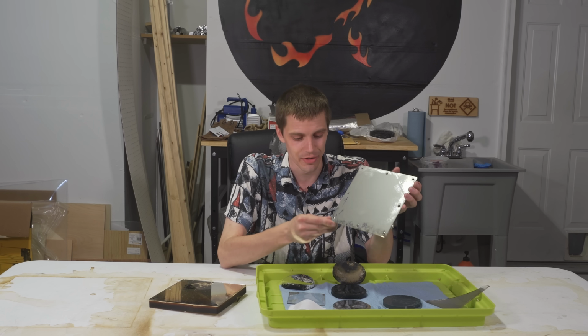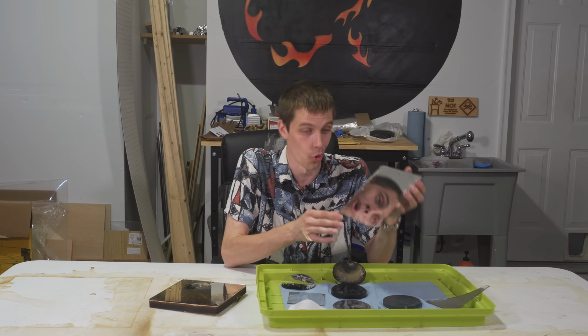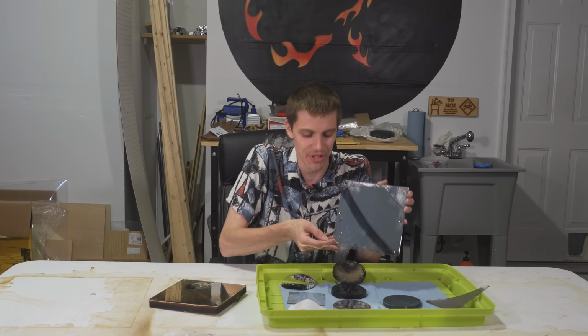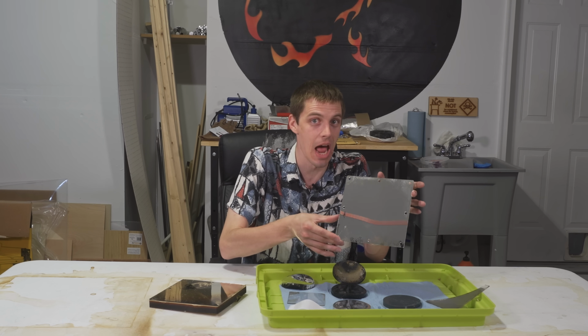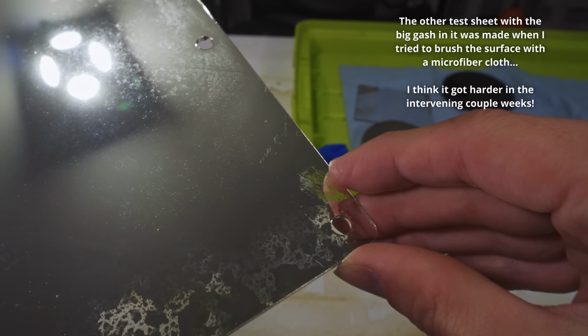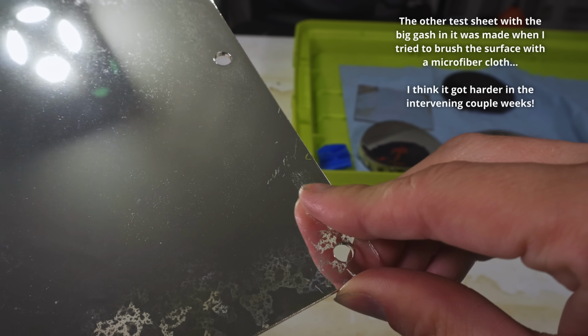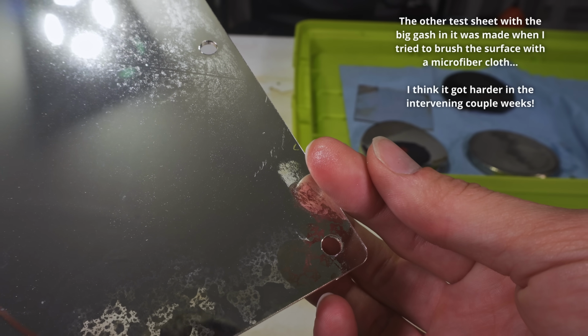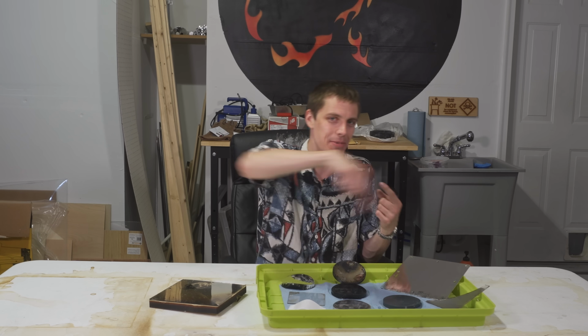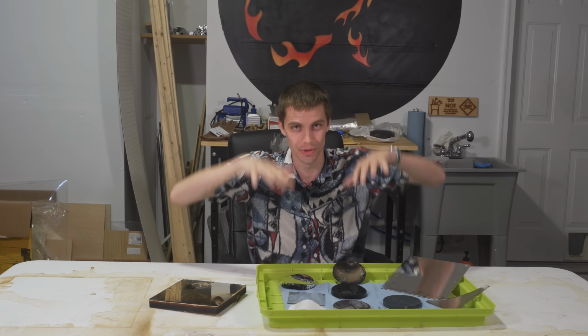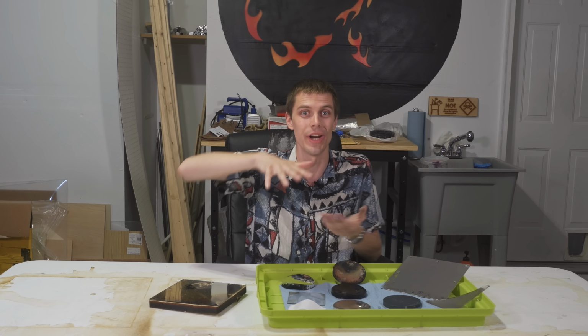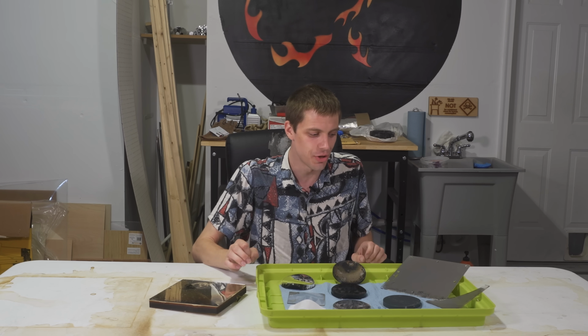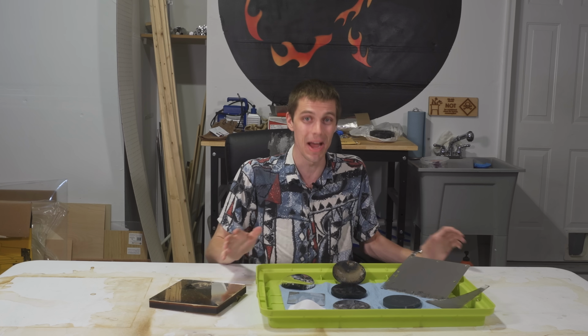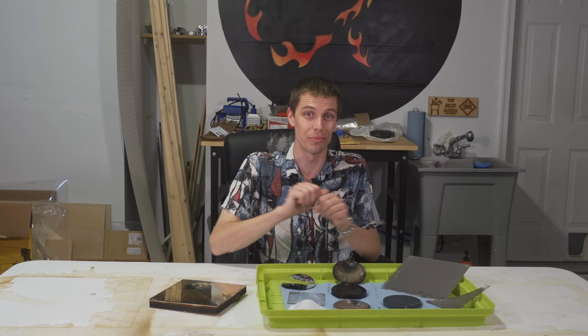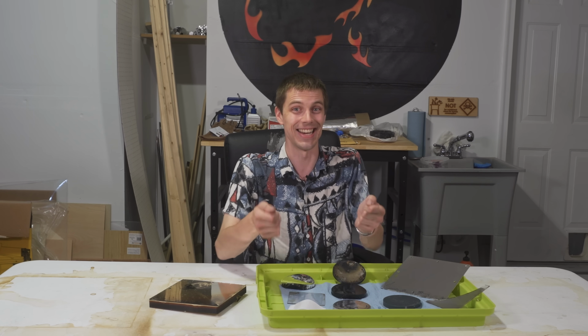This was one of my test mirrors, and literally just me picking it up to hold it in this video, I've gotten some silver to come off onto my hand, and I am not touching the back, because if I so much as brush this, I'm gonna pick the silver coating right off of it. When I took the good mirror to Thinkercon to give to Steve, I had it in my carry-on luggage, all taped up around the edges and flipped upside down, so you were looking at the second surface mirror side with a piece of wood on top of that. So it should have been very difficult to scrape up, and somehow I still managed to remove a good chunk of the silver before handing it to Steve.